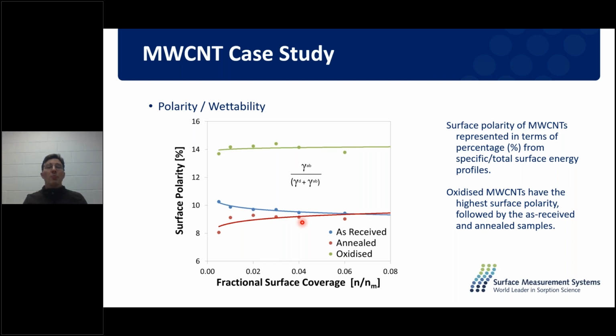And here we can see the polarity or the wettability that has been calculated for each of these samples. Now, polarity or wettability is just a ratio between my acid and base surface energy and my total surface energy. So it's asking the question, what is contributing more to my energy? Is it my dispersive or is it my specific? This is the ratio of what is that contribution. And we can see, no surprise, that our oxidized is, of course, the most polar of the samples.